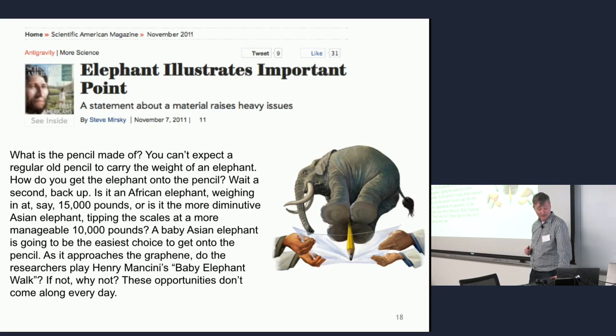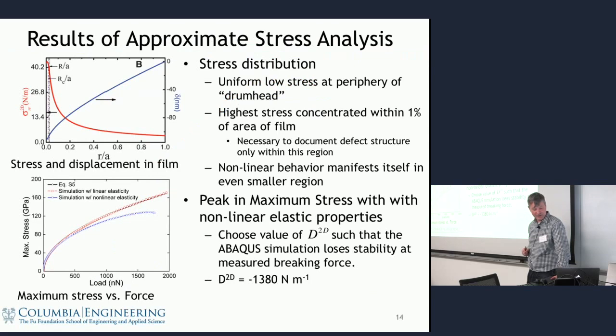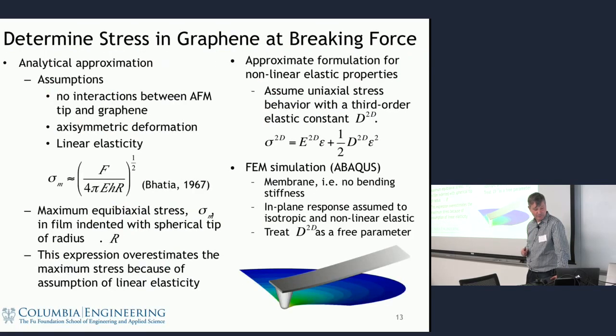So it turns out that my colleague Tony Hines always brings up a nice quote from Einstein that says your model has to be just simple enough, but not too simple. So as simple as you can make it, but not too simple. It turns out this linear term here is way too simple, but even this next more complicated model is still too simple. It actually turns out that when you go to such high displacement, such high strains, if you're going to do a continuum model of graphene, you need a better model than this.